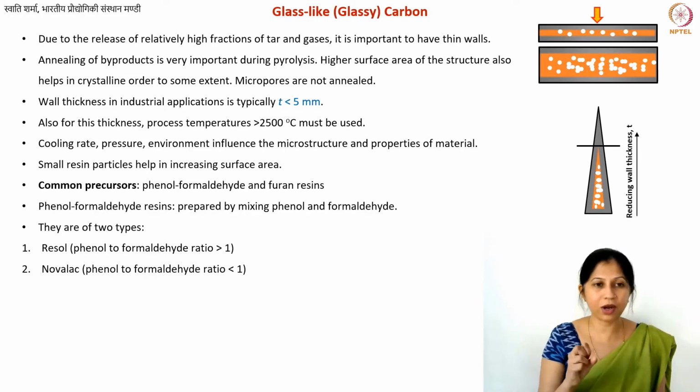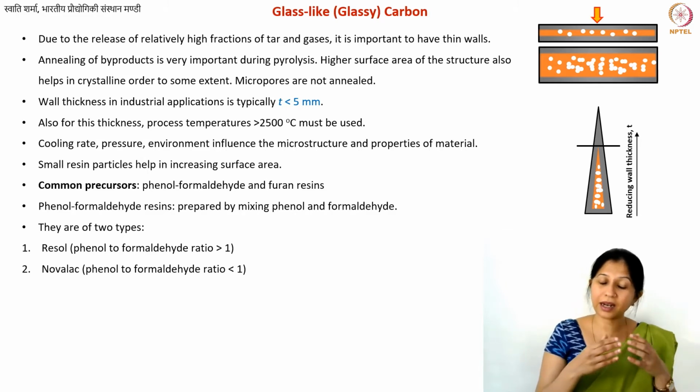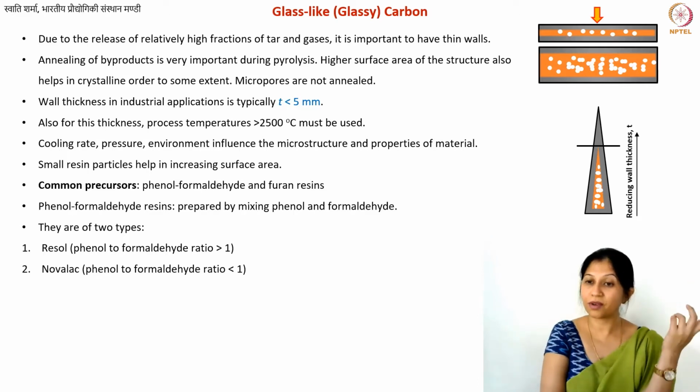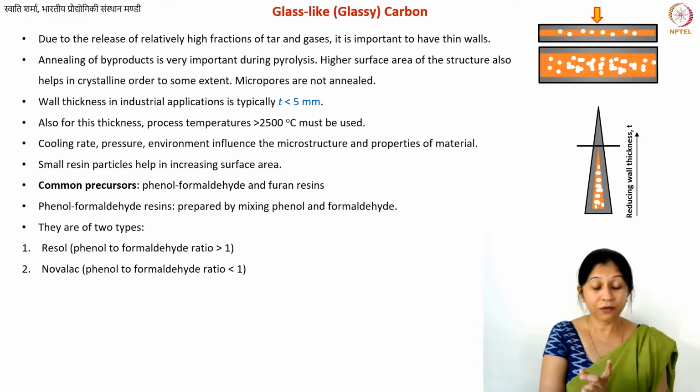Now, typically Novolacs are solid at room temperature and pressure, but Resol materials are liquid. And even within the Resols, by changing the ratio of phenol to formaldehyde, you can get different viscosity of the liquid. That is why you can buy these phenol formaldehyde resins in a range of viscosities, because all you need to do is change the ratio of phenol and formaldehyde, which is very useful for manufacturing applications.